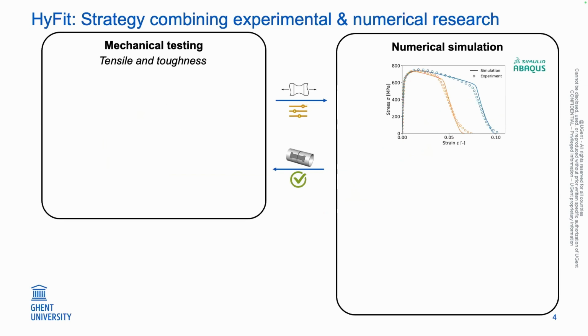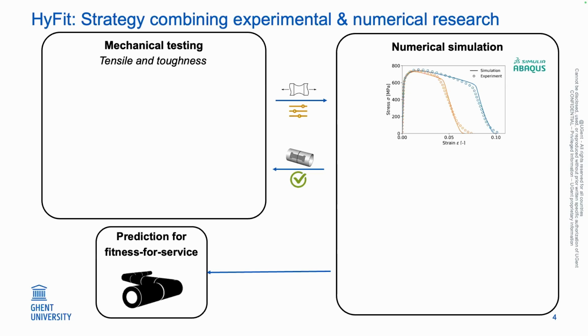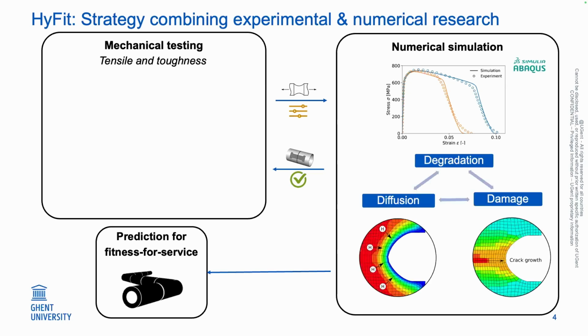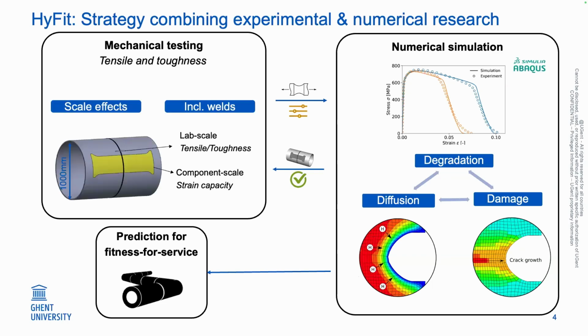There, the strategy is to combine mechanical testing with numerical simulation to, in the end, help the prediction of the toughness of the pipelines. The numerical simulation is based on the model created by Verbeken. It's a coupled model which includes the diffusion, the damage, and the degradation caused by hydrogen. And those are being calibrated and validated by mechanical testing that we do in our lab.